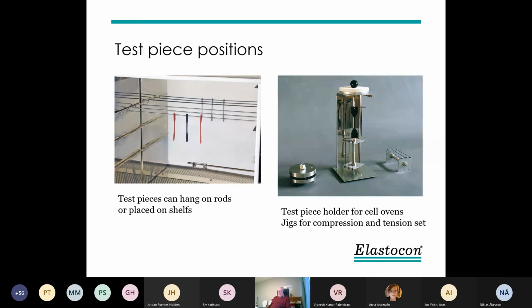In the cabinet ovens, if you are testing test pieces, you can hang them on rods, or if you are testing larger pieces, you have shelves you can place on the positions for shelves. To the right, we have a stand where you can easily load your test piece holder for the cell ovens. And we also show that you can put a compression set fixture or jig in the cell oven, or a tension set jig can be placed in the same cell below the dumbbells. So you test, say, both compression set and aging on one material in the same cell.